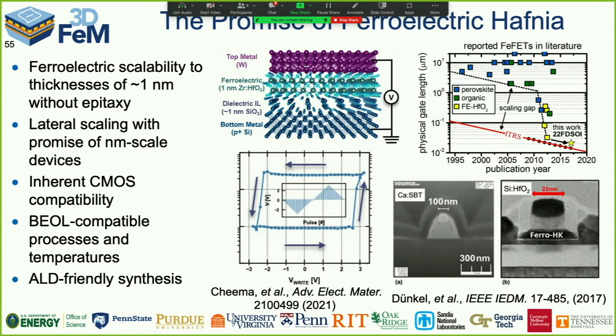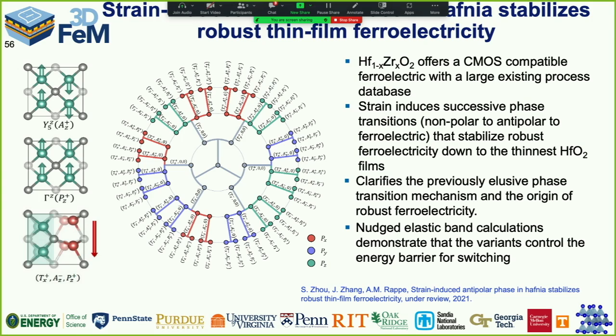You can grow the materials by atomic layer deposition, but nobody knew why it was honest to God ferroelectric. We should probably know this if we're going to engineer with this, particularly if we're going to try and figure out how we beat the coercive fields down by about a factor of 2 to improve the reliability. And so our colleague Andrew Rappe from the University of Pennsylvania has now published a paper where he lays out exactly why this material becomes ferroelectric.